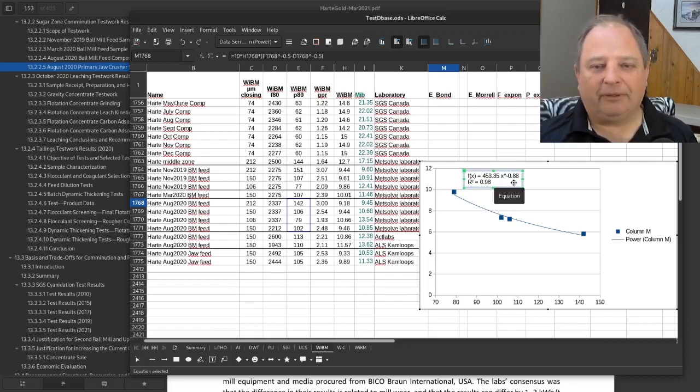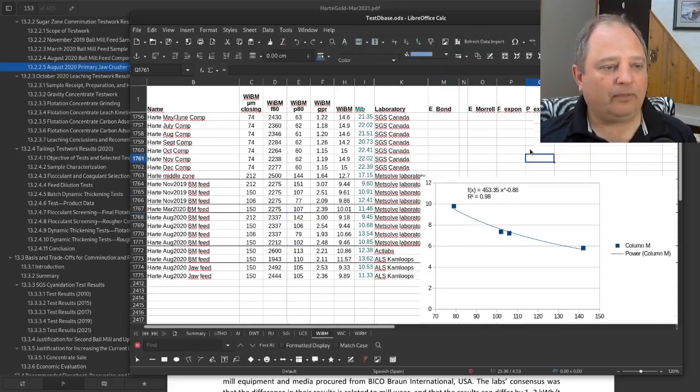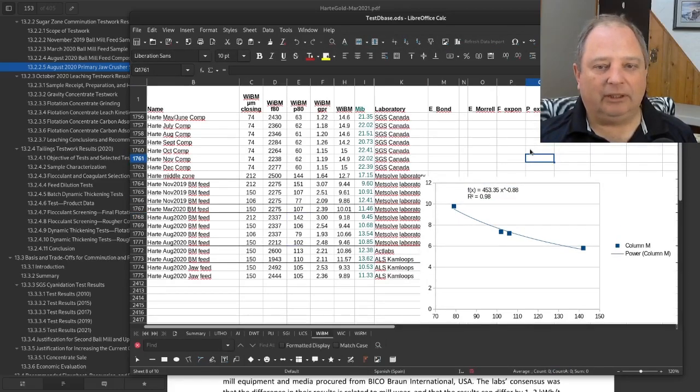And this says a couple of things. Again, I described this in earlier videos. Top level description is that the Bond grindability equations are kind of calibrated for a coarser size than what you're doing a lot of ball milling at. And each ore has its own particular desired exponent. So this is what we're measuring in the signature plot, is what is the exponent that this ore actually wants to use to express itself. So that's that. We've got our signature plot.